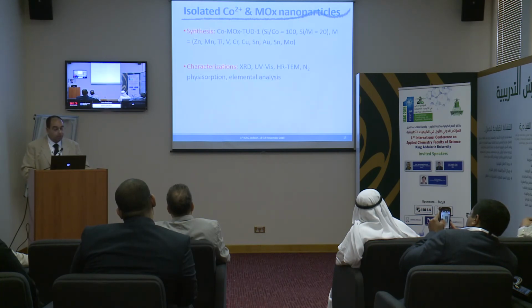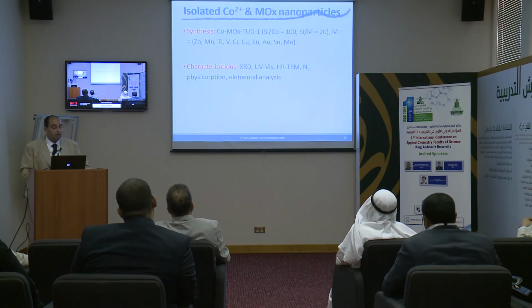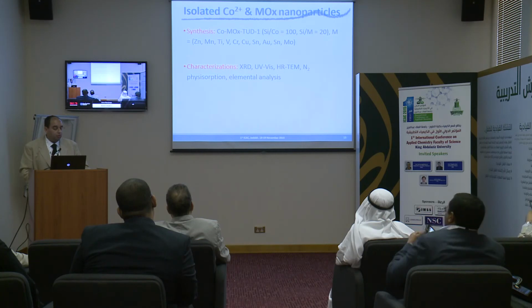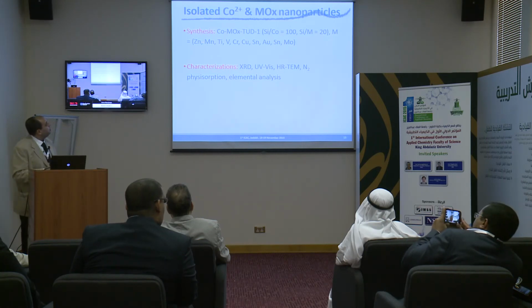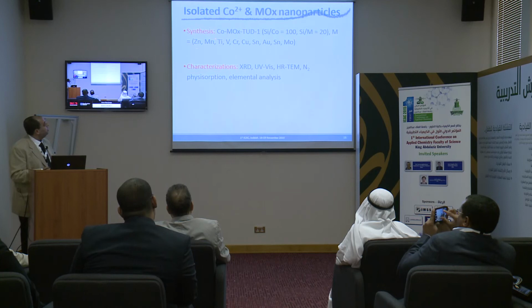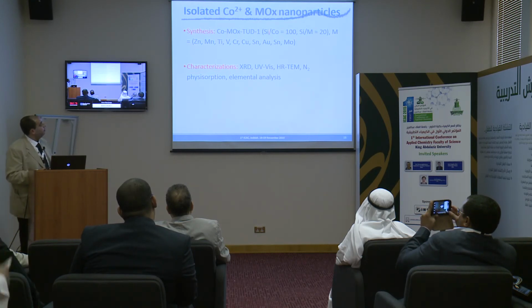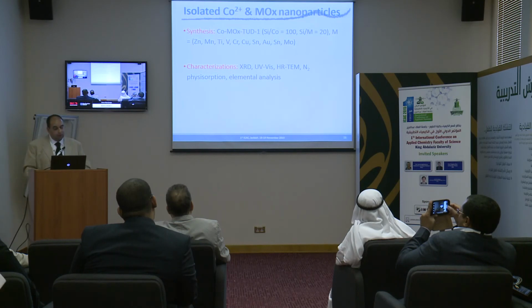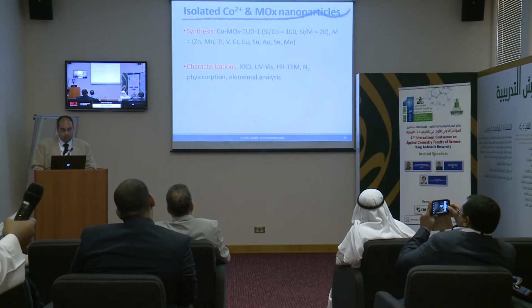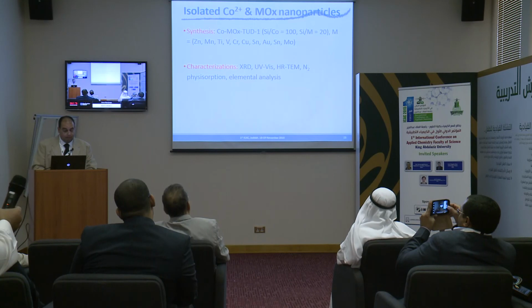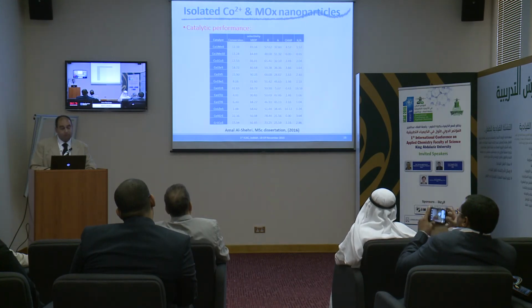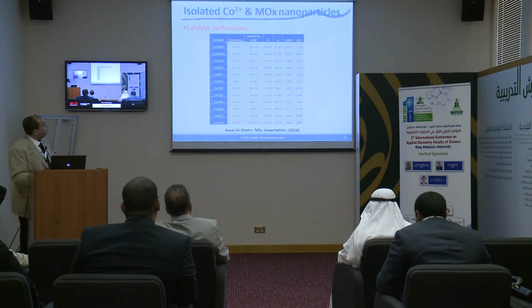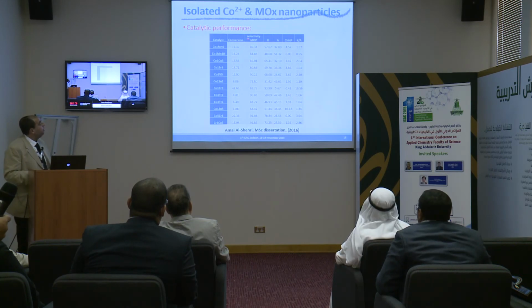We prepared different materials. The base was cobalt supported on silica, including some zinc oxide nanoparticles, manganese oxide nanoparticles, titanium oxide, vanadium oxide, chromium oxide, copper oxide, and so on. We characterized this material as much as we could in our department. And this is the results that we could obtain so far.